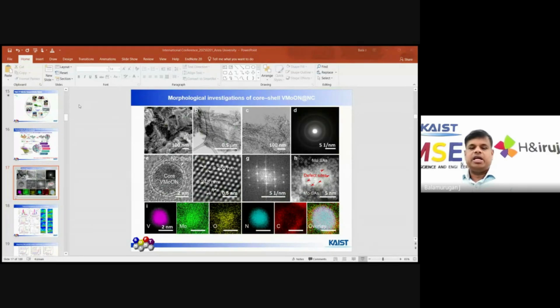After fabricating the materials, we have to confirm the morphology investigation. You can see the same image. There is no restructuring, because very thin nanoparticles as well as single atoms may be homogeneously distributed over the networks of the graphene. And you can see there is no metal nanoparticle observed from the SAED patterns, because the single atoms may be finely distributed over the networks, and the core-shell is around 2.4 nanometers, with a core of vanadium molybdenum nitride in the networks.